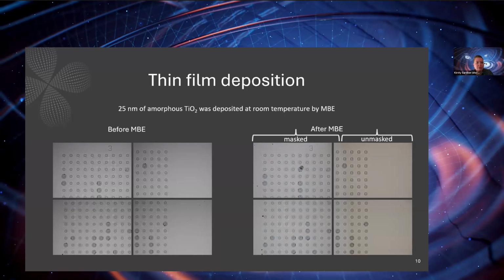And so the next step after fabrication is to deposit the thin film. So we deposited recently 25 nanometers of amorphous titanium dioxide at room temperature by MBE. And generally the way that the measurement for mechanical loss of the film is done is that you take 2 measurements. You measure a device when it's bare, uncoated, and then you do a second measurement when it's coated. And there's a formula that relates those 2 measurements. You measure the quality factor.